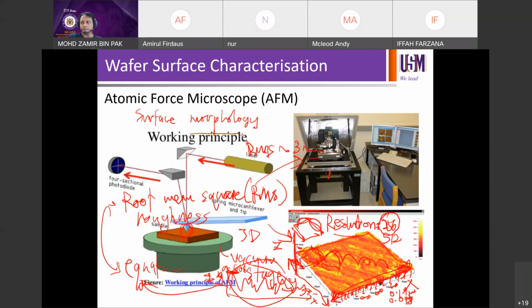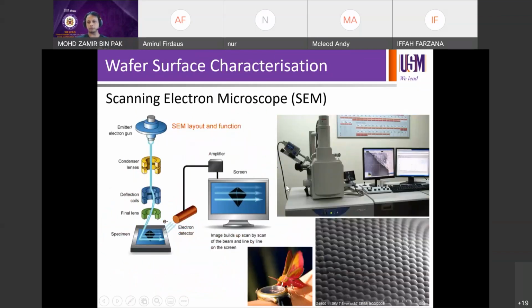On the other hand, if you're working with features hundreds of nanometers in size, you'll probably be seeing RMS roughness of about 30 to 50 or 100 nanometer, depending on the height, the dimension, the uniformity, and many other factors. But that sort of magnitude is the difference between smooth and rough. You can even get hundreds of nanometers as your RMS roughness if you're working at micro scale, especially. So try to relate that to the experiments that you've done before.